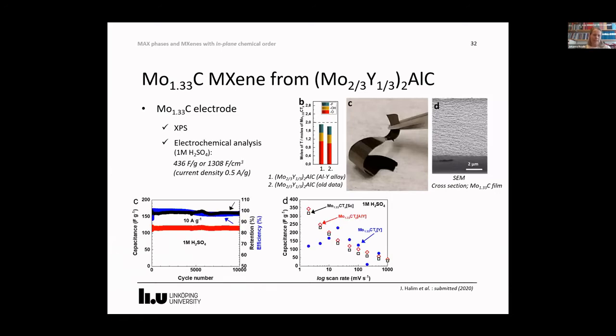So if we now take our optimized MXene from Mo2/3Y1/3 MAX phase, we can turn it into a highly flexible film without any additives. And here you also see a cross-section SEM. As expected, the XPS analysis shows very similar surface terminations if we compare our old and new MXene synthesis approach. We also did some electrochemical analysis in 1 molar H2SO4, but I will not go into detail as the behavior is the same as our previous studies on the MXene.